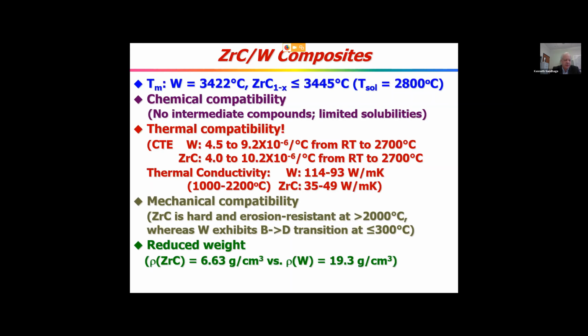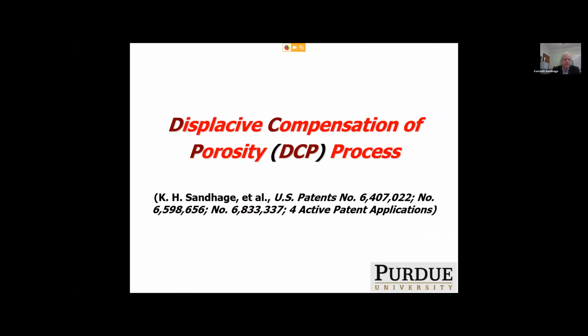Of course, if you're launching something, you want it to be as light as possible. Tungsten is, of course, quite heavy, 19.3 grams per cubic centimeter. As much tungsten as you can replace by ZrC, the better off you are for achieving a lighter weight material to launch. So we think this combination of properties, as exotic as the cermet sounds, is really well suited for this particular application. And like I said, we searched for this combination. It wasn't by accident that we picked it.